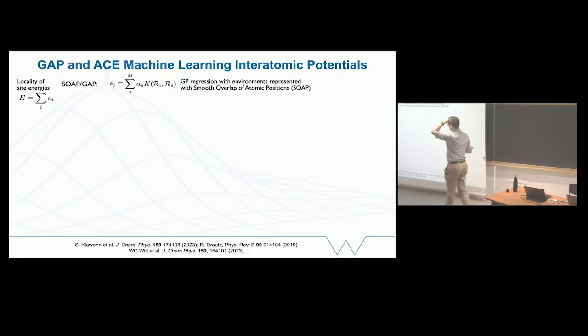The SOAP GAP approach, as a descriptor, actually uses something called SOAP, the smooth overlap of atomic positions. The way that works is that you sit on an atom, you find your neighbors. On each neighbor, you place a little Gaussian, and this gives you a density field. You can add up all of those small Gaussians, and you have a density. You then need to find a way to compare that density with another density in a way that gives you rotational invariance. This is the tricky part.